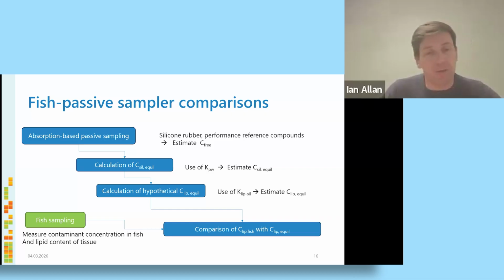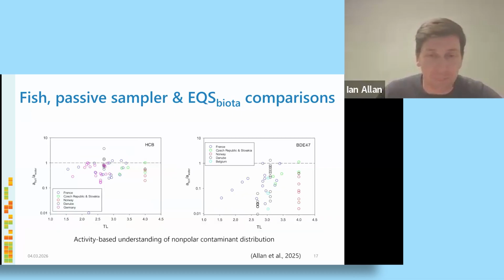And then from that concentration in silicone, we calculate a concentration in lipids that essentially would be at equilibrium with the water that we've sampled with our sampler. So from the passive sampling in water, we end up with a concentration in lipids that would be at equilibrium with that water. And then we take the fish data, concentrations in the fish on the lipid basis, and then we can try to compare these two values to see simply how they compare. And then we'll see that on the next slides.